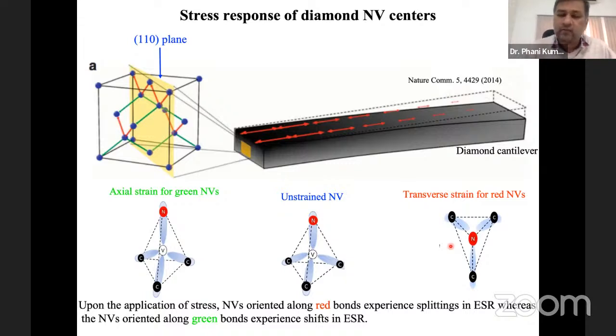I talked about electric fields, and now I will talk about stress fields and how we can understand the interaction of stress fields existing within the diamond lattice with the NV center. We have a diamond lattice. It can be intrinsically strained. For example, if you take a polycrystalline diamond, it can be strained because of grain boundaries, or you can mount this diamond sample in a diamond anvil cell and apply uniaxial stress or hydrostatic stress. Or, for example, here you have a diamond cantilever. You can make diamond cantilevers by etching techniques.